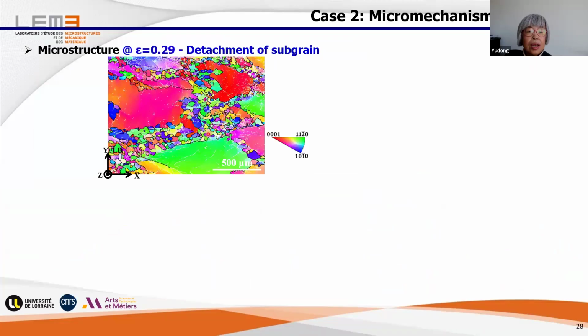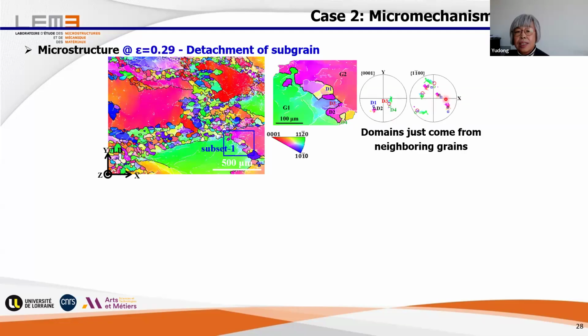Deformation, we see now, the boundary of the coarse grains is now decorated by these fine grains. The question is, are these fine grains from a new nucleation, or from the already bulging part, and the bulging part further evolves with a different deformation mode and increases the orientation difference from the matrix grains? Then a simple pole figure analysis.